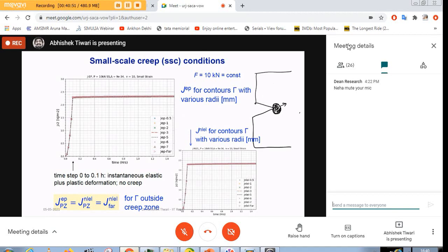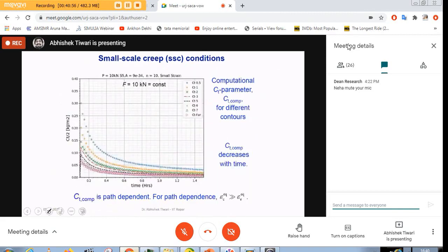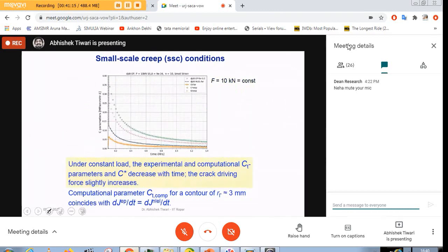For that we calculated the J integral using configurational forces, and we calculated the C integral with the concept which already exists. As I said earlier, it is found that the C integral is path dependent, so it varies if you take different contours. So we cannot use this idea in the small scale creep at least. But if I find the rate of change of the J integral, dJ by dt, it defines something. Because J is the crack driving force, the rate of change of that defines the rate of change of crack driving force with respect to time.